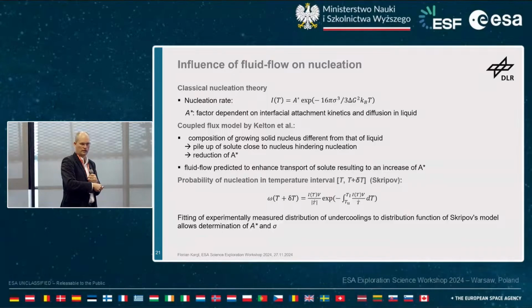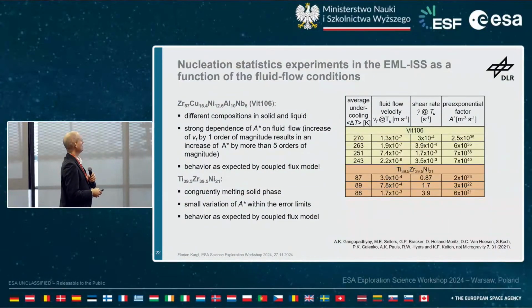You do quite a number of experiments, actually quite many. And you plot, let's say, this undercooling statistics, simply how many times did you solidify the material at a particular undercooling. And then you can describe this curve with this model. And from that, you can derive two important parameters, this A star parameter here and the sigma parameter. And you can compare that.